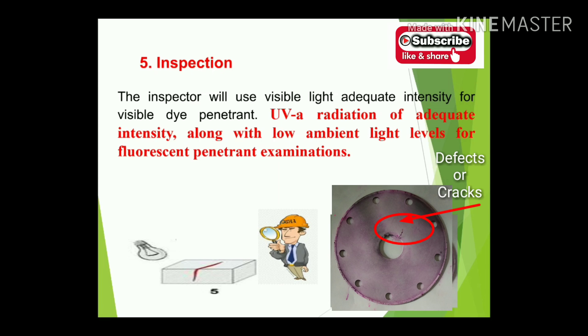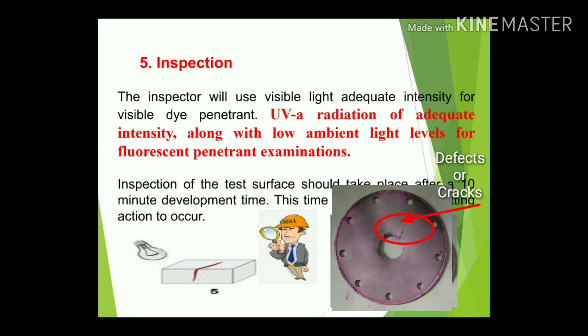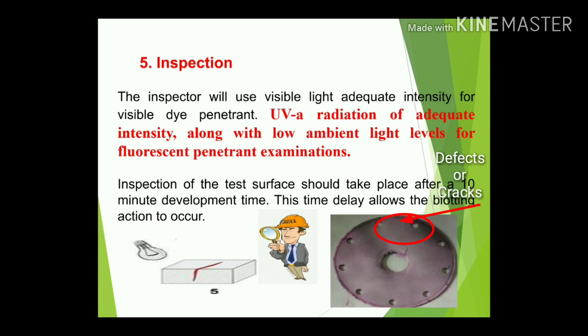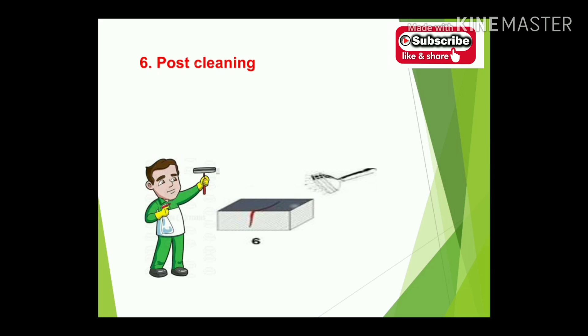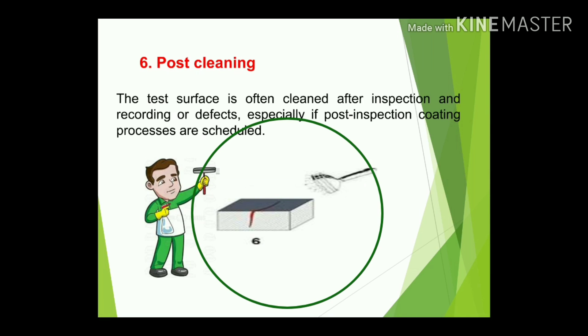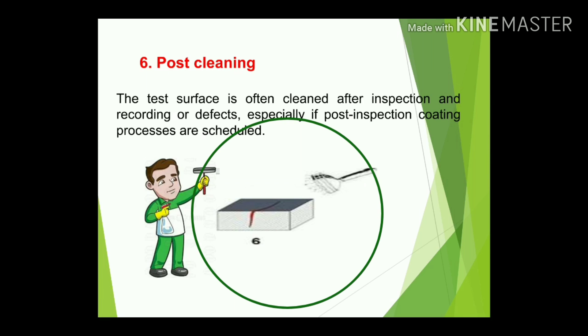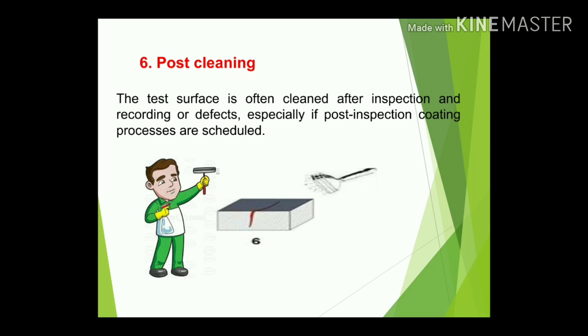You can easily identify irregularities or cracks. The inspection of the test surface should take place after 10 minutes of development time, allowing the blotting action to occur. The final step is post-cleaning: the test surface is often cleaned after inspection and recording of defects, especially if post-inspection coating processes are scheduled.